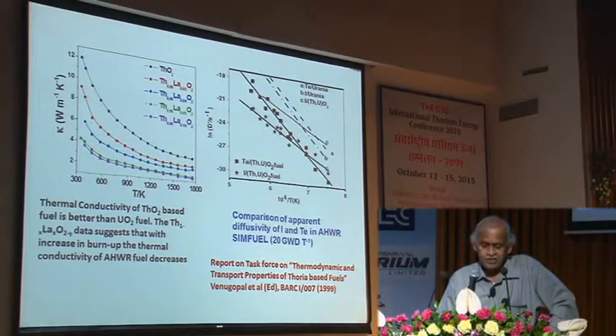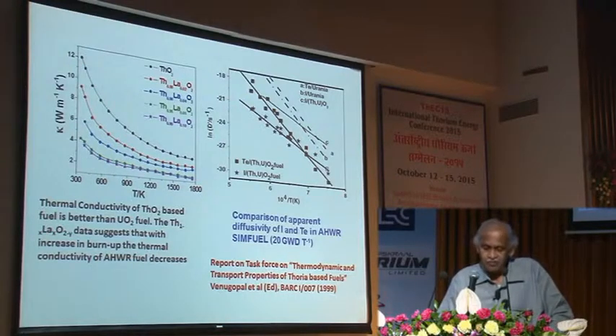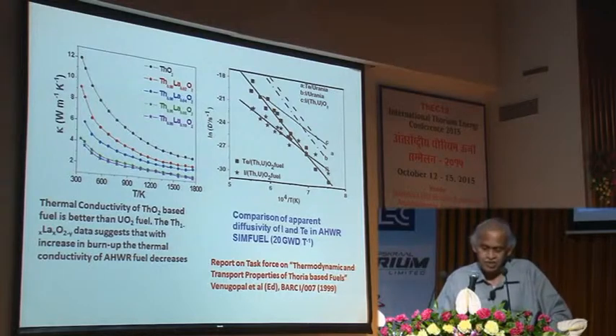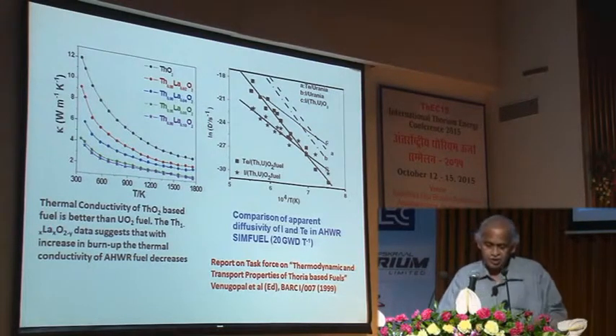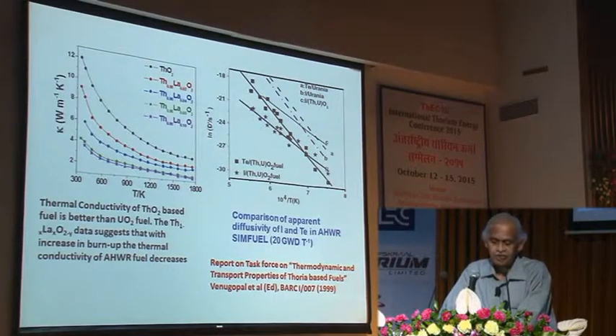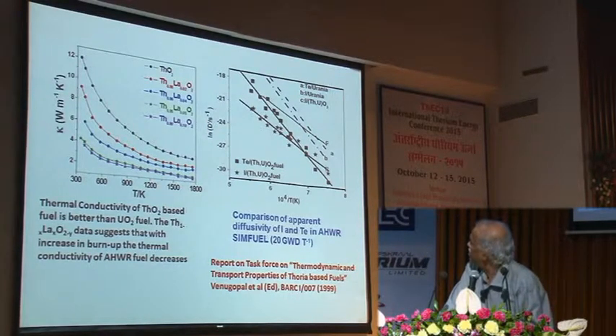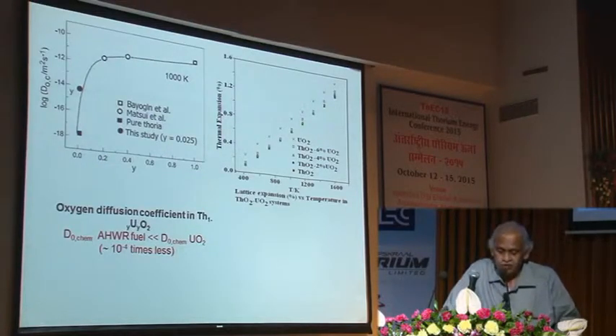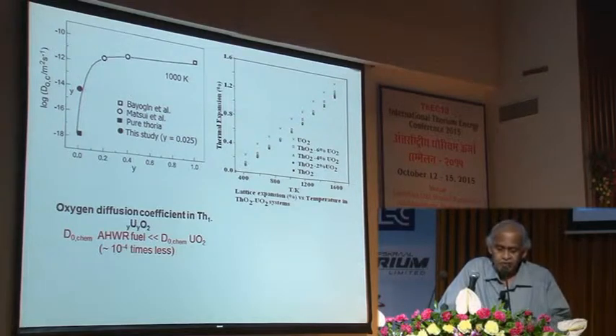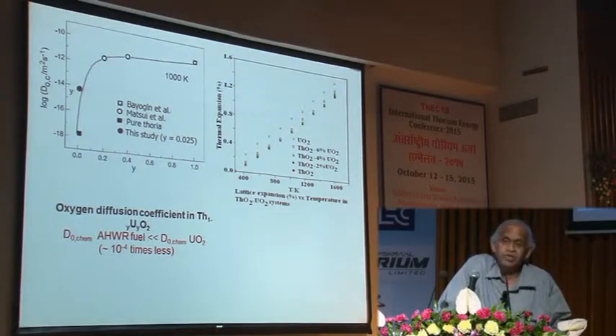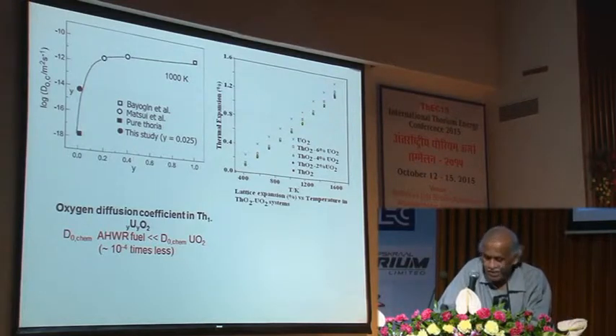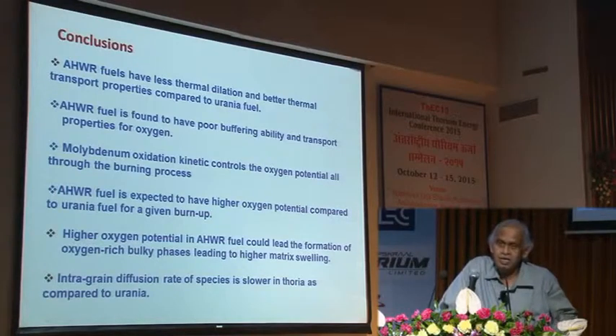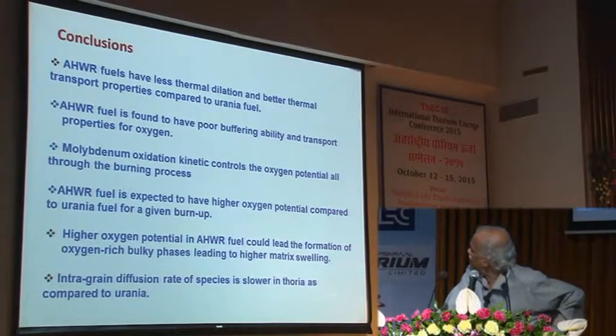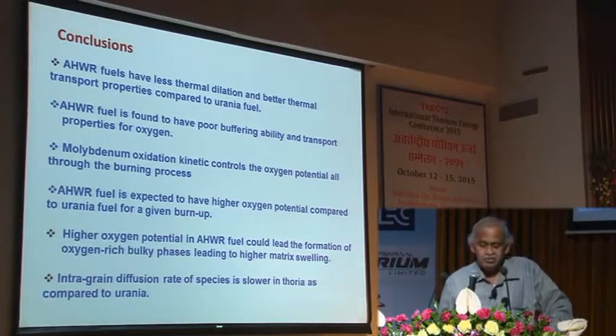This is something which would be taken as an input while taking a decision with respect to the AHWR fuels. Similarly, for the comparison of apparent diffusivity of iodine and tellurium in AHWR SIMFUEL, that has been synthesized, and we published this with respect to iodine and tellurium diffusivity in AHWR fuel, which indicates how tellurium and iodine compare to each other, as shown in this graph. And of course, oxygen diffusion also has been studied, and the diffusion coefficient in AHWR fuel is far less than what we normally come across in uranium oxide. It is almost 10 to the power minus 4 times less. So this is how the data that could be produced were used in designing the fuel. So the conclusions: AHWR fuel has less thermal dilation and better thermal transport properties.